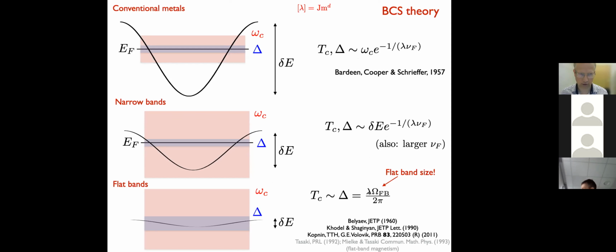And interestingly, as you can also see in the previous settings, the density of states is an intensive property. So its dimension is 1 over energy, 1 over length to the power d, where d is dimension, which means that this lambda also has to have a dimension of energy times meter to the dimension. And therefore, in order to get an energy from here, you have to multiply this constant by another constant, which in this flat band limit is the size of the flat band in momentum space.